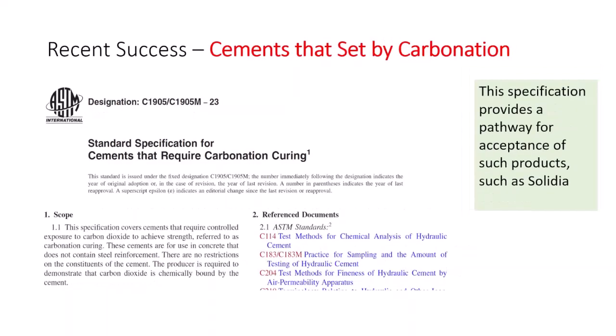So it's this test that is a predictive test. There's a brand new standard that just came out in the last couple of months, for cements that set by carbonation, to allow some of the materials that don't hydrate, they set by carbonation. So they sequester carbon. There are a couple of companies out there, such as Solidia, that use a wollastonite type of calcium silicate that binds with CO2. It doesn't harden on its own. It hardens with the presence of CO2. And there's some other companies taking advantage of that too.